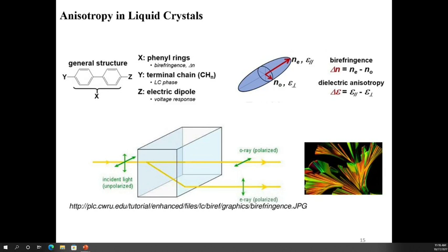So you can picture it as a half nanometer length and a half nanometer width. So we consider this as having the birefringence property, which means when an incident light goes in, it will split the light into ordinary and extraordinary waves. When those waves come out of the liquid crystal material, because of the interference between those two pathways, they're going to generate different colors based on the retardance distance of those two paths. It will reflect different colors here.